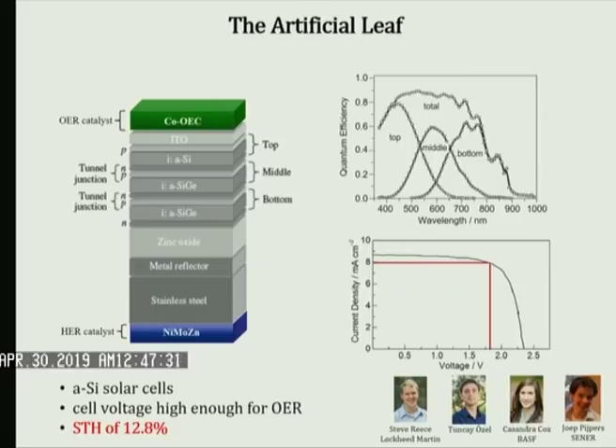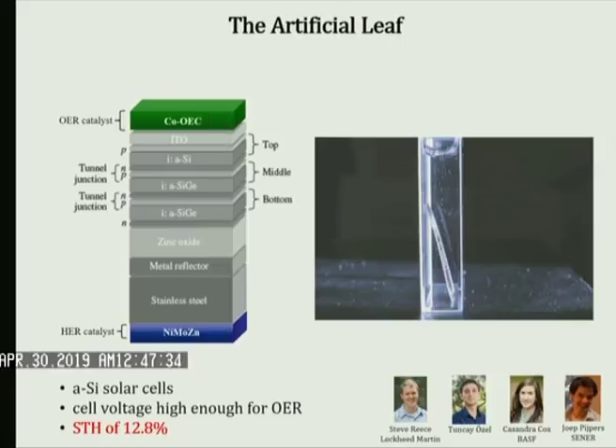So now what happens? Just like in your solar panel on your house, the sun hits the silicon, and I get separated moving charge, and I get 1 unit of charge, and it gets injected into the cobalt self-healing catalyst that makes oxygen. The electron goes to the bottom. We set this up so it's biased. The electron goes down, and the hole goes up. The electron goes to the hydrogen catalyst, and that's 1 unit of charge, and I inferred before you need 4 units of charge to make oxygen, 4 holes and 4 electrons. So you do that 4 times, and when the cobalt gets charged up, oxygen comes out.